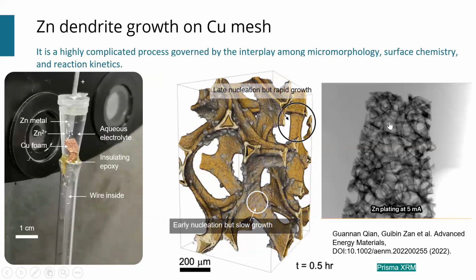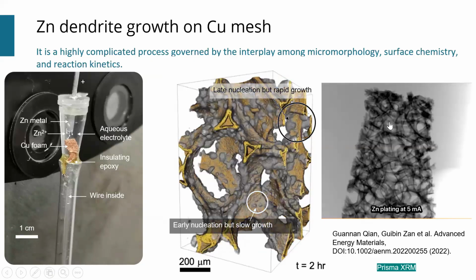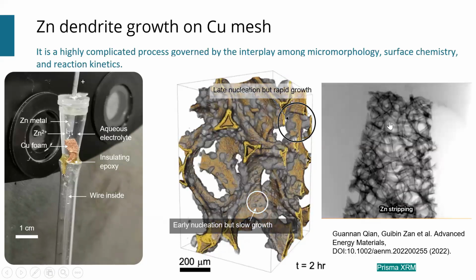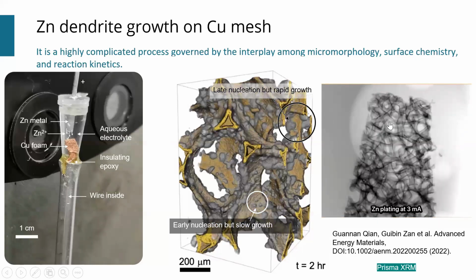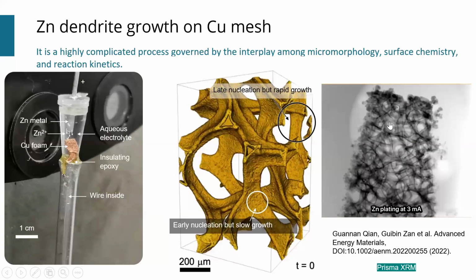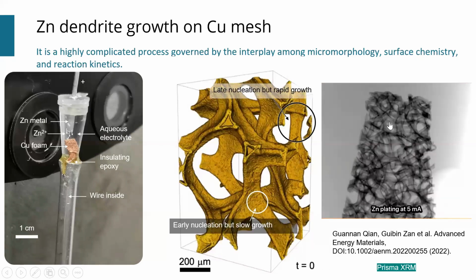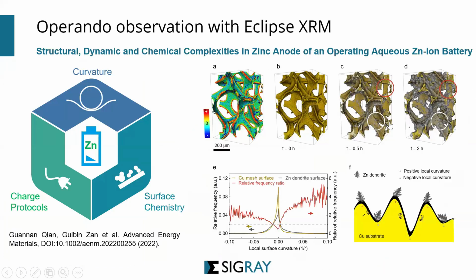So now let's take a look at the in Operando or in situ experiments. Here is a simple example where we are looking at the electrochemistry during the deposition or nucleation of zinc dendrite on a copper mesh. So you can study nucleation in 3D, and from there you can derive the various mechanisms where it's shown that during early nucleation, the time is slower, but in late nucleation, you find that there is an avalanche of all those precipitations that has happened, and all these dendrite formations can now be modeled in situ.